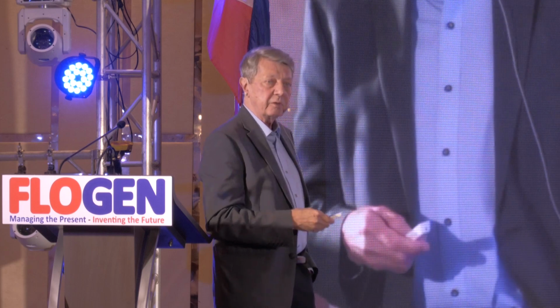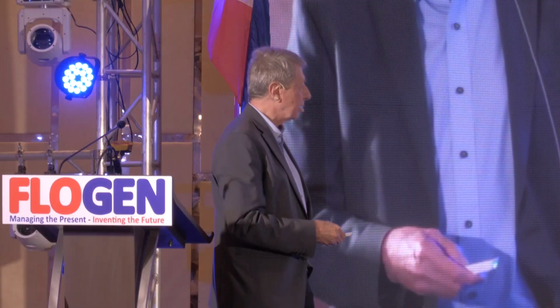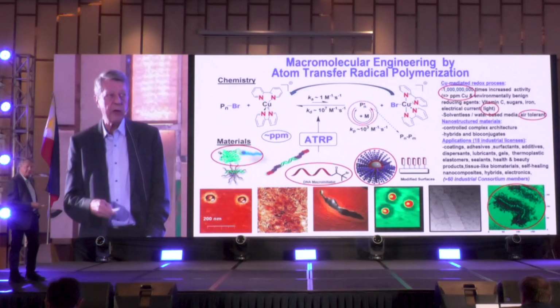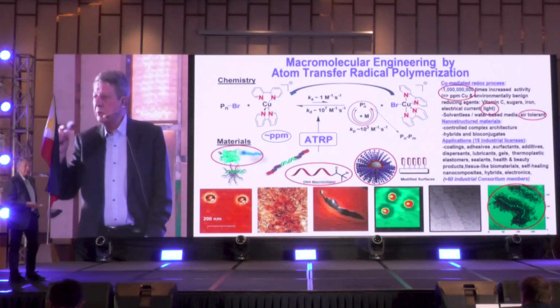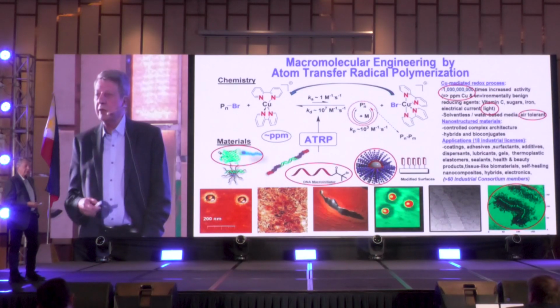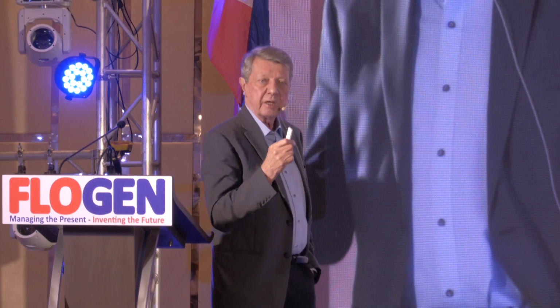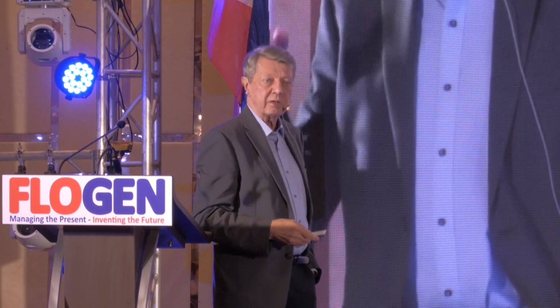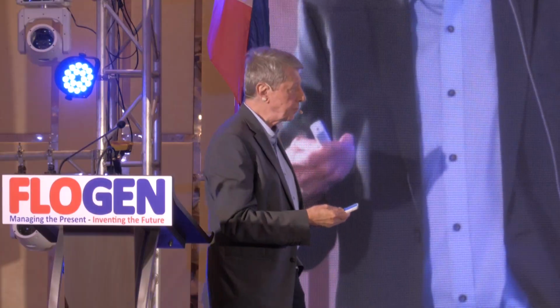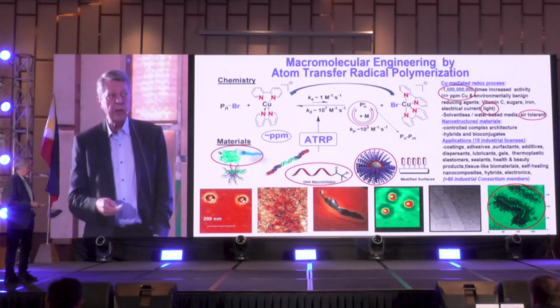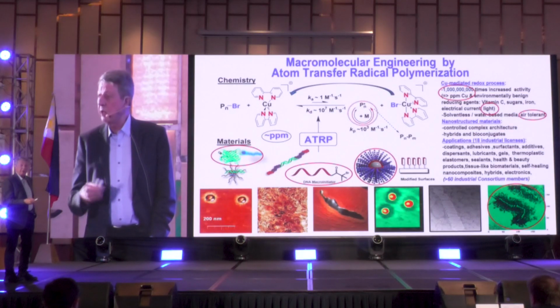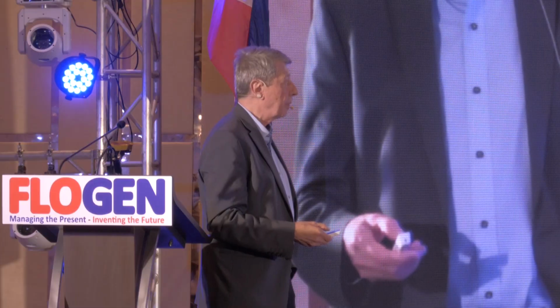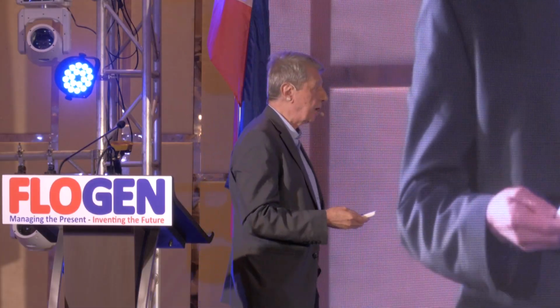So this opens the possibility to make polymers, but also very sophisticated structures, like these bioconjugates, or decorating nanoparticles with polymers, or putting a 10 nanometer layer on the surface of whatever material you have. And these 10 nanometers will make the material surface antimicrobial, or anti-fouling, or super lubricious, and change properties dramatically, having only less than 1% or 0.1% by weight of the entire material. So this is really relevant. We have 18 industrial commercial licenses, and we have over 60 industrial consortium members learning how to make these materials in the future. So, the next slide.